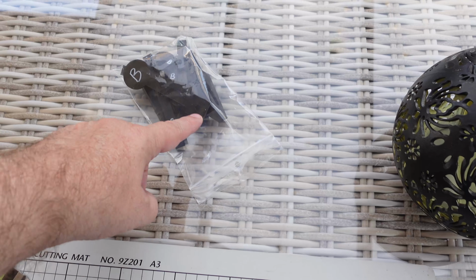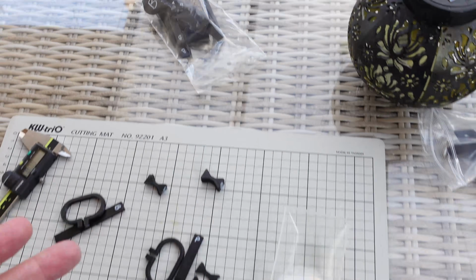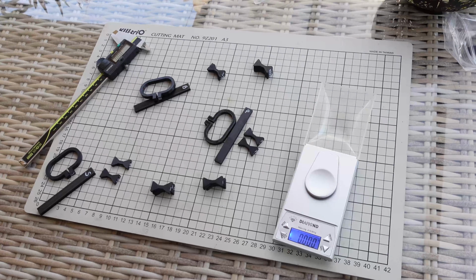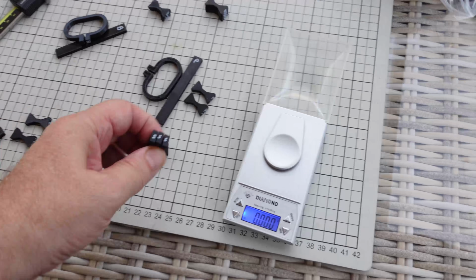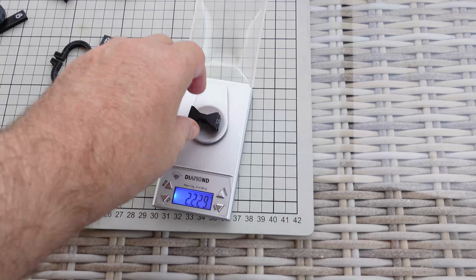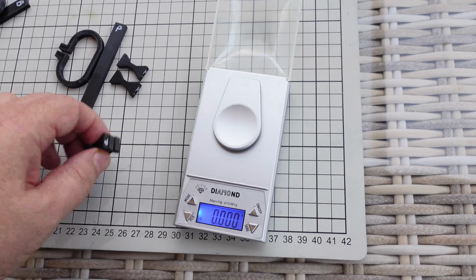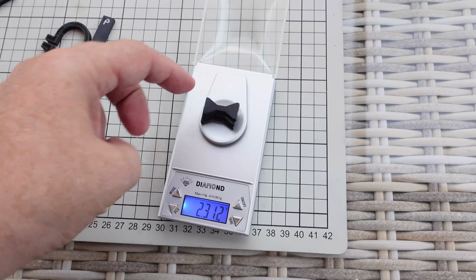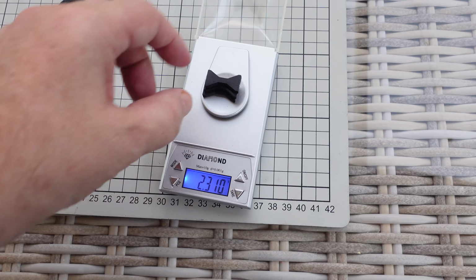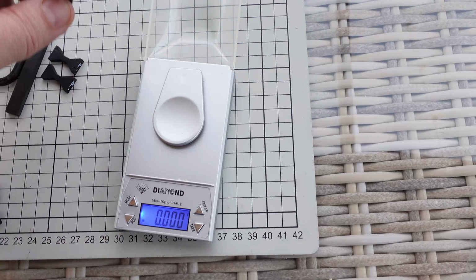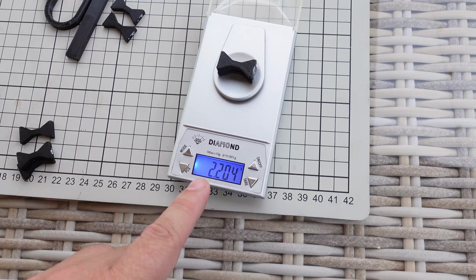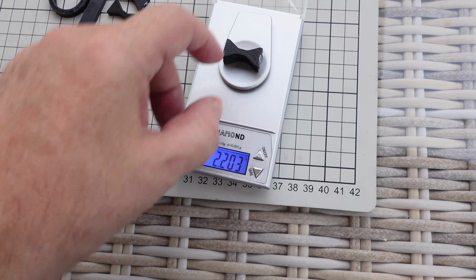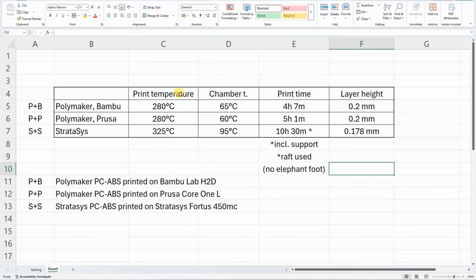This is quite a big difference, almost 4%, so I decided to do more measurements, but in front of the camera just one, for the tensile test. Stratasys, 2.313. Prusa, 2.310, very close. Bambu Lab, 2.203. Here I collected the printing temperatures and the printing time because it is very different, and it is important